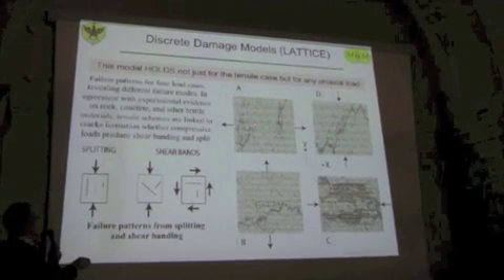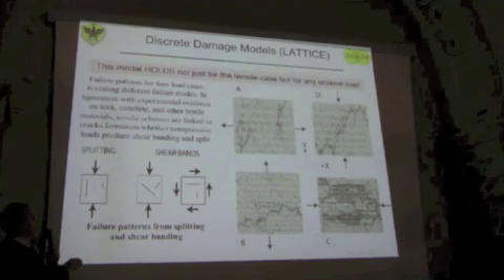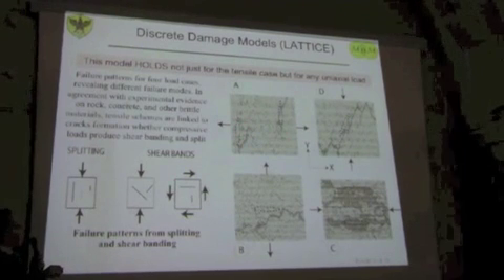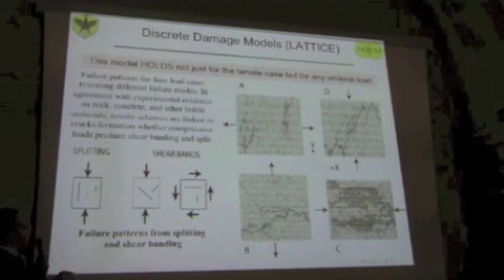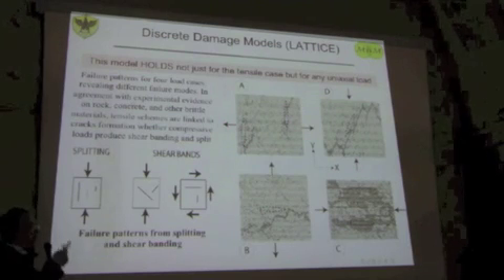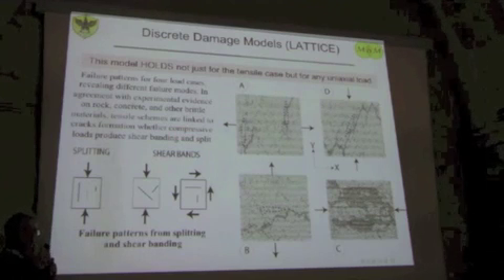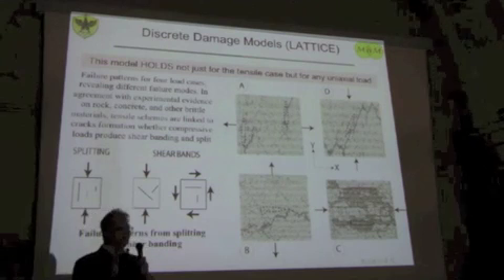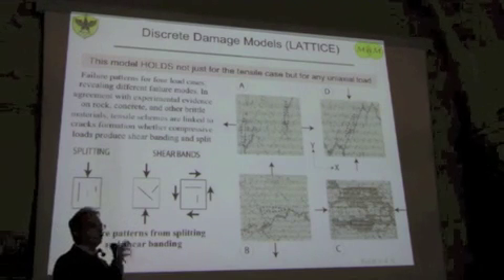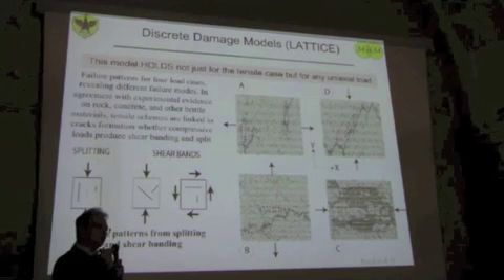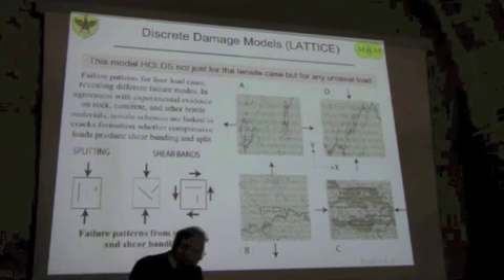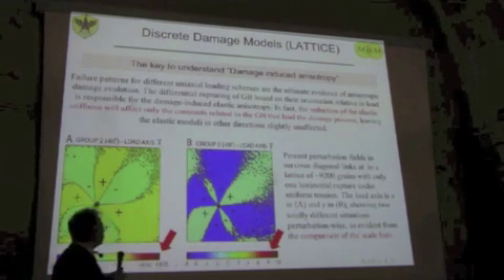And of course, if you're able to track the system, the phenomena, and you're able to measure those quantities throughout the damage evolution, you will be able to essentially predict really nicely the behavior of the lattice for not only tension, but also compression, and not only in X, also in Y, because of course this lattice is not really isotropic. It has anisotropy. I mean, it's isotropic only in pristine state, because the hexagonal lattice maps into an isotropic continuum. This is well known. But as soon as you introduce one defect, you induce an elastic anisotropy. So a damage-induced elastic anisotropy.